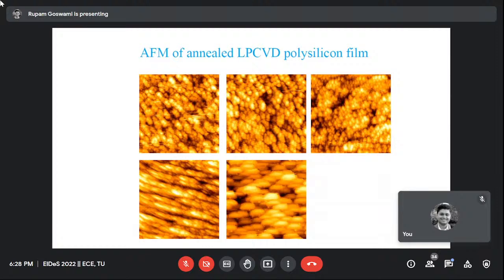So this is a clear indication that if we have the grains either in cluster form or elongation form or final form, and we use these as a basic initial polysilicon film, and then we do the doping of boron, and then we measure the performance, certainly it will be different. So these are the possibilities. We can introduce the technology in tuning the properties of the pressure sensor by changing the piezoresistive coefficients.